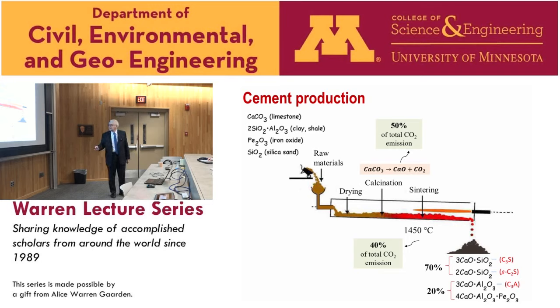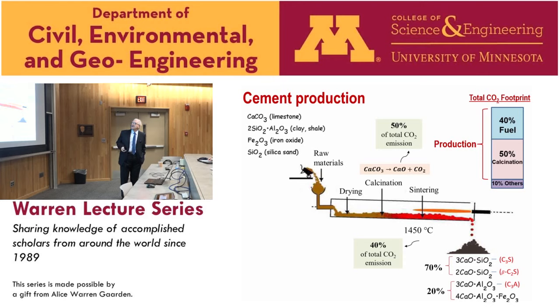But anyway, those two compounds we'll be looking at in terms of sustainability and what we can potentially change in making the binders more sustainable. If you look at the energy balance and associated CO2 footprint, you will see that about 40% of energy associated with the manufacturing of Portland cement is associated with generating this high temperature, fuel burning. And about 50% comes from decalcination of calcium carbonate, or limestone, and 10% distribution costs and others.